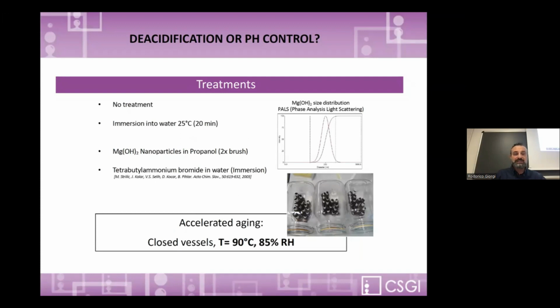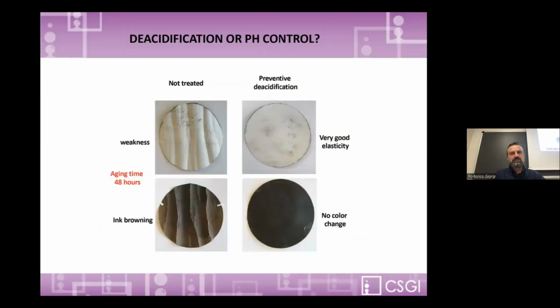And then we compare different treatments, which is the effect of simple immersion into water, that implies the removal of the excess of iron that is obviously soluble in such condition, and the comparison of a treatment with alkaline nanoparticles and with a classic antioxidant, for example, tetrabutylammonium bromide in water. Then we apply some aging method, classic hydrothermal accelerated aging, high temperature, high relative humidity.